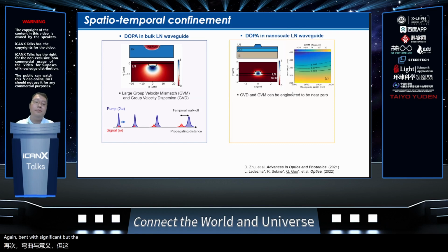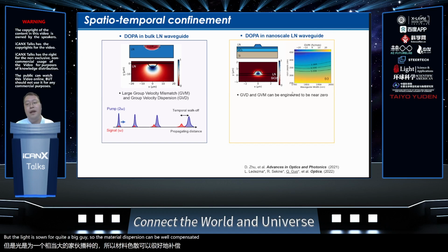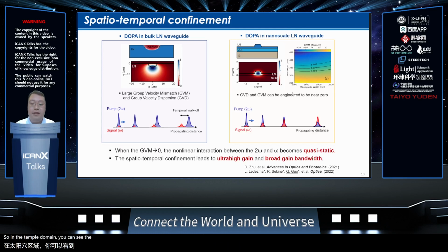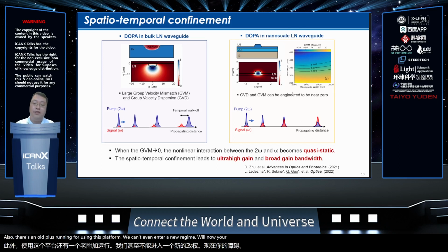But in thin film lithium niobate waveguide, as you can see here, the light is so confined to the waveguide. So the material dispersion can be well compensated by the modal dispersion of the waveguide. By carefully designing the geometry of the waveguide, we can even engineer the GVD and GVM to be close to 0. So in the temporal domain, you can see the pump and signal can always be overlapped. This can make the parametric interaction super strong. And also because the GVD is close to 0, there's no pulse broadening. So using this platform, we can even enter a new regime of nonlinear optics, which offers a very large gain